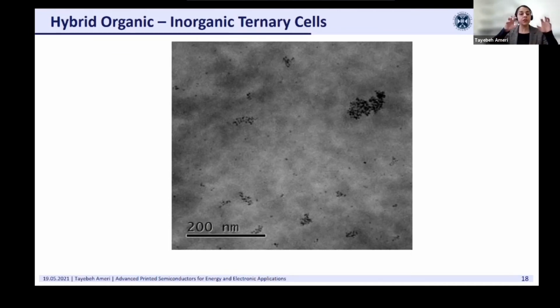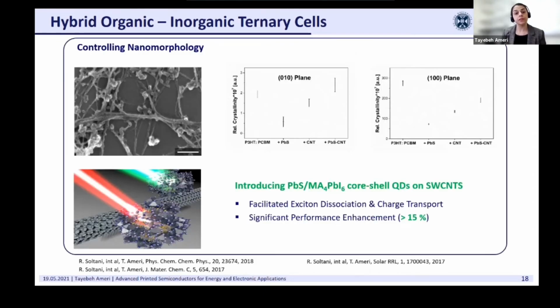We may fix the position of our quantum dots on a template like carbon nanotubes to avoid their agglomeration at high concentration. And here you can see how successfully this idea worked when we introduced our lead sulfide quantum dots on the carbon nanotubes. Then we were able to preserve the morphology and ordering of our host-rich P3HT:PCBM in both the pi-pi stacking and lamellar stacking directions, while introducing any of those components individually has a negative impact. And in this way, we were able to achieve a significant performance enhancement of over 15% for our hybrid systems.